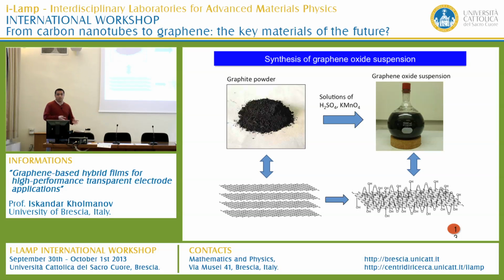So another type of graphene we used is produced by wet chemistry methods. This is completely different from CVD grown graphene, and the most attractive feature of this fabrication is low cost. So you do not need any vacuum or high temperature furnace. To produce graphene oxide, the starting material is a graphite powder, whose grains are composed of a layered structure of graphene, and by chemical treatment, we can exfoliate graphene layers and obtain highly dispersible graphene oxide. This is even dispersible in water, because our graphene now is not actual graphene, but graphene oxide.